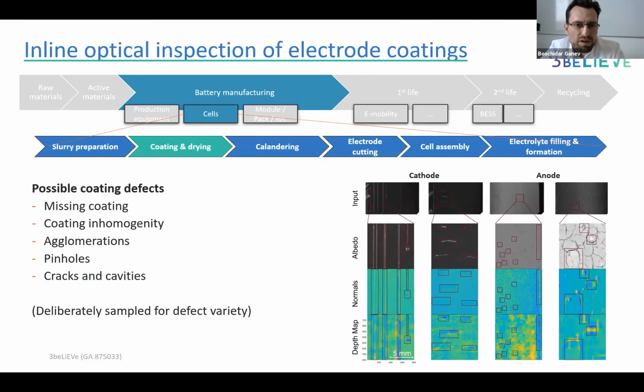So the first on the battery manufacturing level. As we know, in the electrode coating process, when it comes to the deposition of the slurry, sometimes it can occur that we have an inhomogeneous deposition of the slurry. So that can lead to coating defects. That means there can be too little coating in some parts of the electrode or too much material in other parts. And this can manifest as scratches, as pinholes, as cracks, as agglomerations.